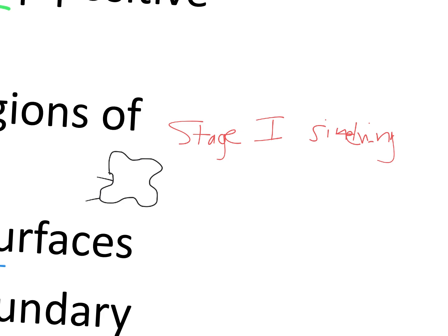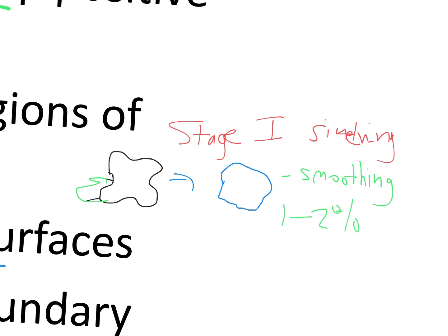And so what that means is that as this thing heats up, we see what's called an immediate smoothing. I'm going to try to do this justice, but I can't guarantee. So we're trying to make those initial jaggedy areas smoother by causing transport from the hills to the valleys, basically. That's happening all over, and so it's smoothing these particles. And this is certainly very true of nanoparticles, because they're really jagged. True nanoparticles have facets, very tiny, sharp points on them. That's the first thing that goes away when you heat these up. And that stage one sintering is not very important in terms of getting to our goal, only 1-2% volumetric shrinkage. But it's an example of how this process can drive material behavior.